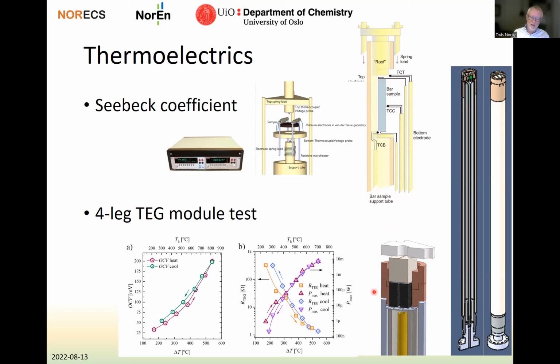So in this way, we can use the ProboStat to study thermoelectrics at much higher temperatures than other sample holders. And we can study interconnects, for instance, between the legs. Here are some results from a recent paper showing the open circuit voltage of the 4-leg module as a function of temperature difference and the top temperature. And here we plot the resistance of the module and the output power as a function also of the temperature difference and the top temperature.